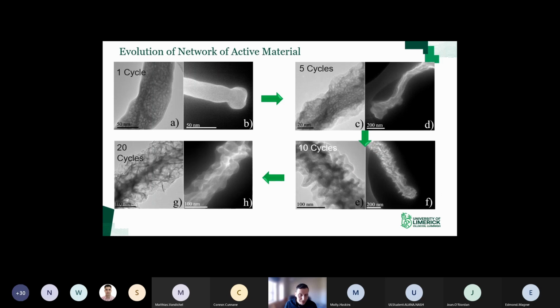We looked at the evolution of this process in a little more detail on TEM as well. What we saw was after 1 cycle, if you look at a nanowire, you can see pores started to form. Basically, you alloy the material and then you discharge it, so you de-alloy it, but that leaves behind a vacancy where the lithium has been. Those vacancies aggregate and form pores, and there's an energetic driving force for that because it reduces the overall surface area. As you continue to cycle, the pores begin to aggregate, so you can see the pores get larger and the surface of the nanowires get rougher.